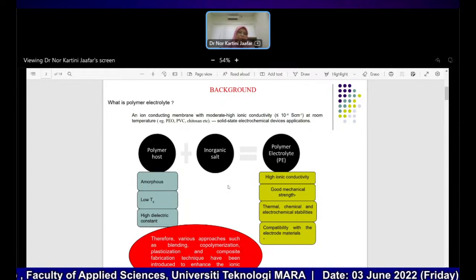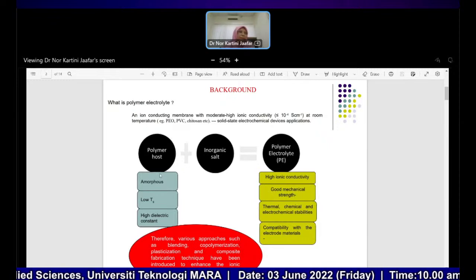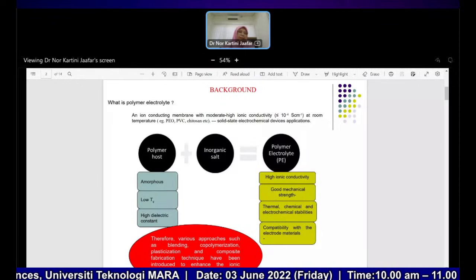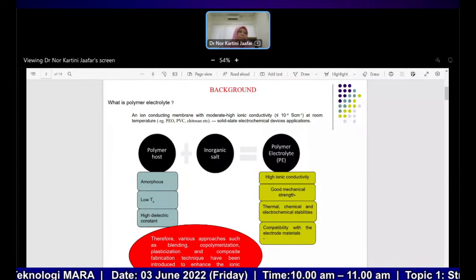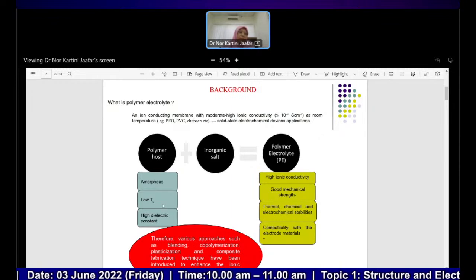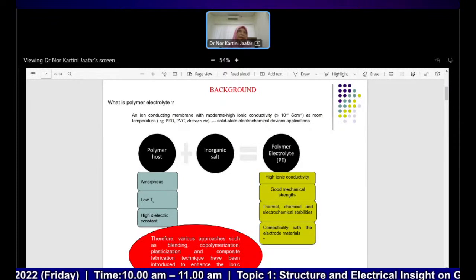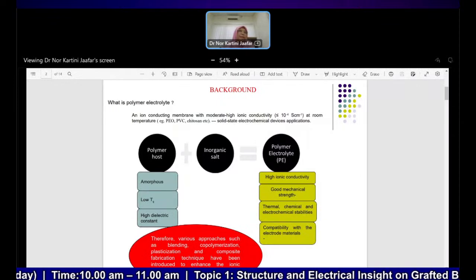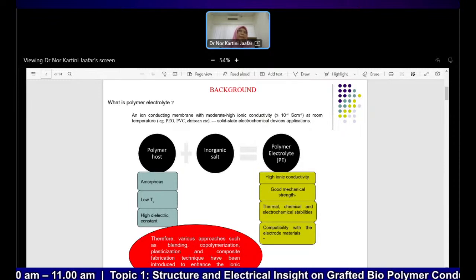So the polymer host itself must have good enough amorphous characteristic, to allow the ion moving or transport within the polymer, and then low glass transition temperature and a high dielectric constant. With the high dielectric constant, it makes it easy to store the ion within them, and it helps dissociate the salt to become ions.